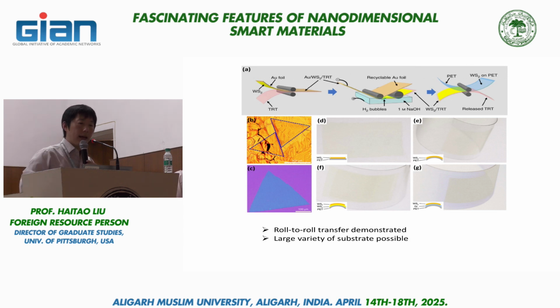metal substrate. And from there you can also, at the same time, attach a flexible plastic substrate receiving the TMD. This, in a lot of cases, can be a thermal responsive plastic. And from there you can just press them together and pull them apart, and magically the interaction between the TMD and the plastic substrate is stronger. And then there's additional hydrogen evolution that creates the exfoliation effect on the metal side.